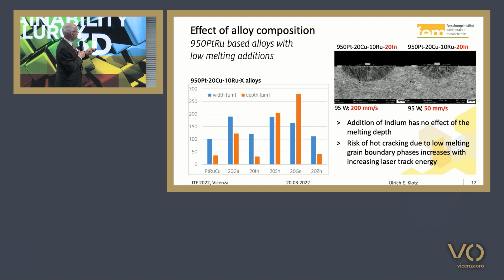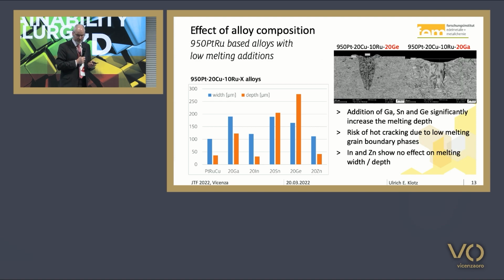We see that the width and the depth are influenced differently. Here's the platinum ruthenium copper alloy, and we see indium, zinc have little effect. But other alloying elements like tin, germanium, or gallium have a very strong effect.